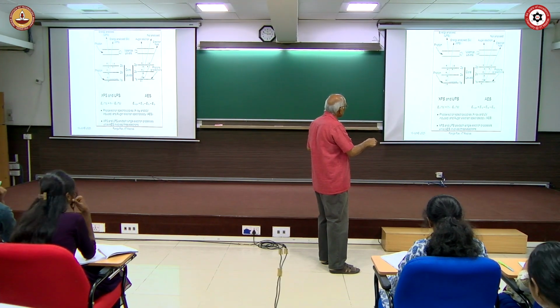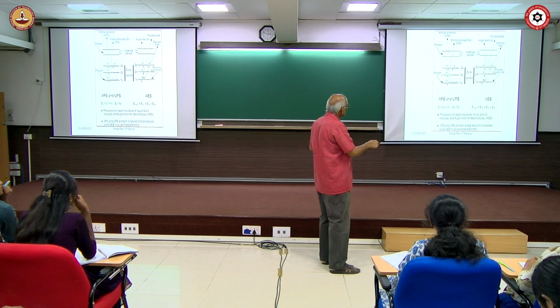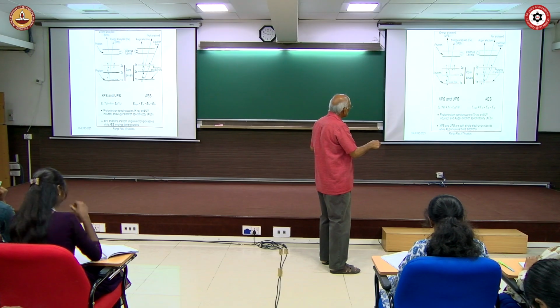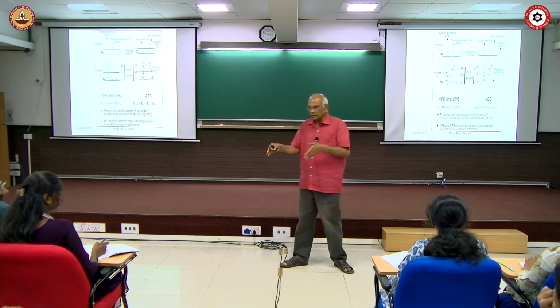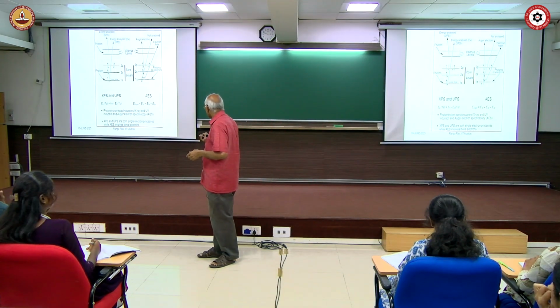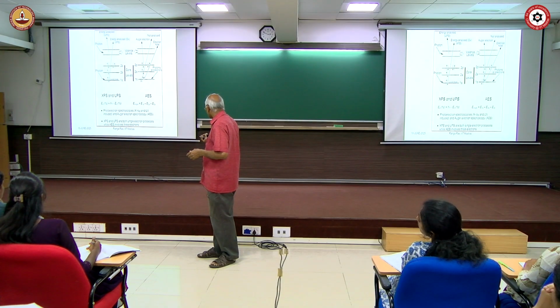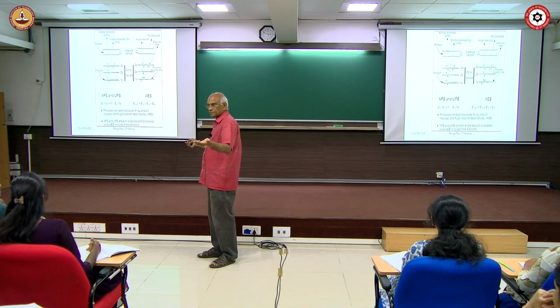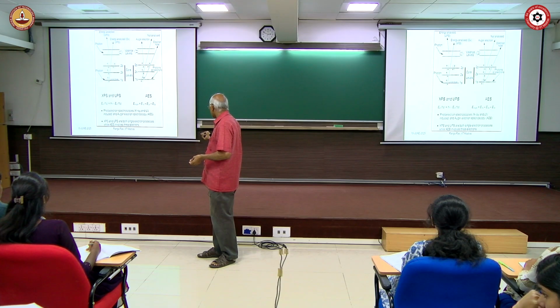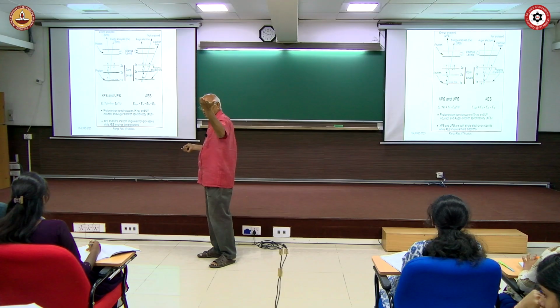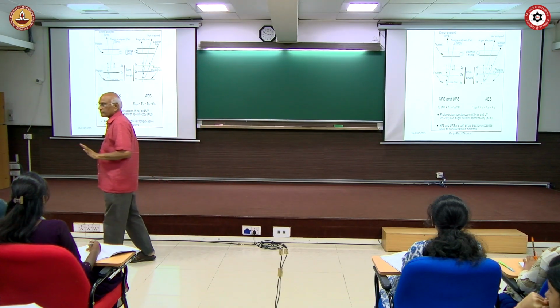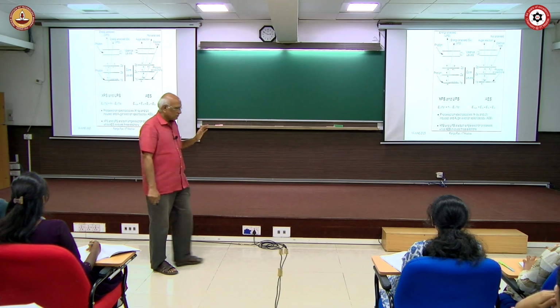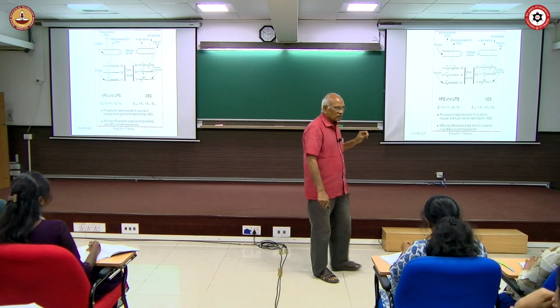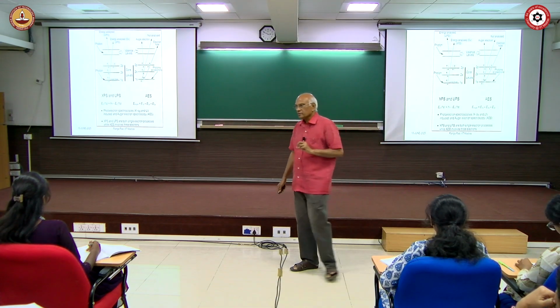So these are the core levels. These are all, you can call them, core levels. Now a second process that happens here is, once you create this core hole, this is a very unstable, excited atom. So then what happens is, an electron from a higher level jumps into this level here, and that energy difference is released as X-ray. And that energy sometimes can be picked up by the electron sitting in a higher level, and then it will come out. That is nothing but the Auger electron, right. But the Auger intensity is very low. Very few Auger electrons come out.